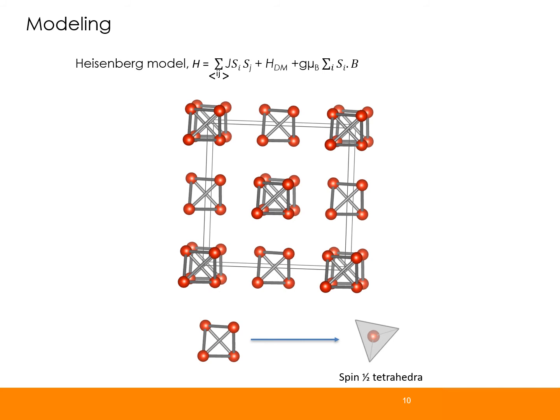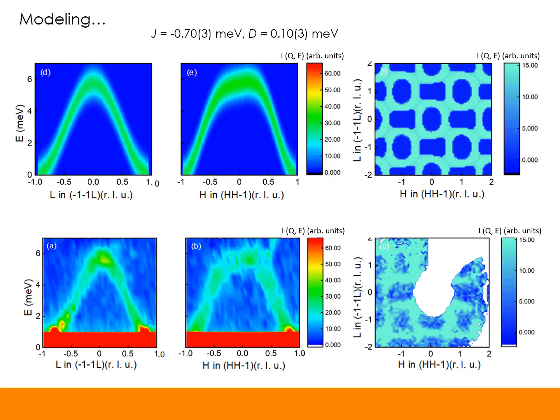And for the model, we know in this material that there is a single spin associated with each B4 tetrahedra. So I localized the spin at the center of mass of each tetrahedra, and then modeled the spin excitation. By doing this, I was able to reproduce the excitation spectrum which we measured experimentally. The upper panels show the theoretically calculated excitation spectrum, and the lower panel, which I showed in the previous slide, is the experimentally observed spin waves. The spin waves obtained from the model have the same energy scale, and the features are very close, meaning that the model is capable of reproducing the spin excitation spectrum.